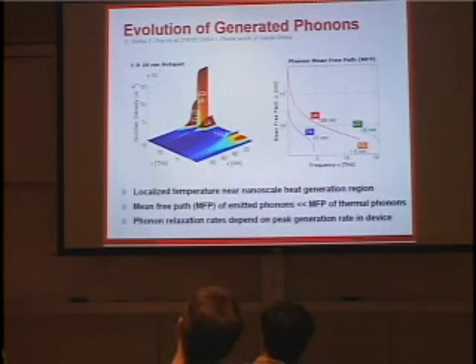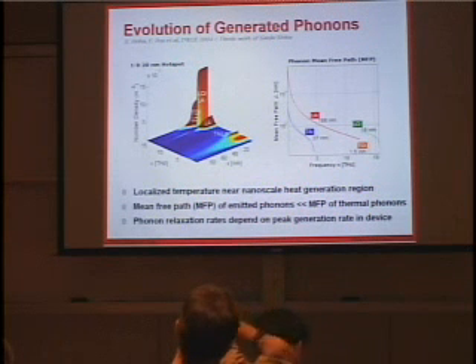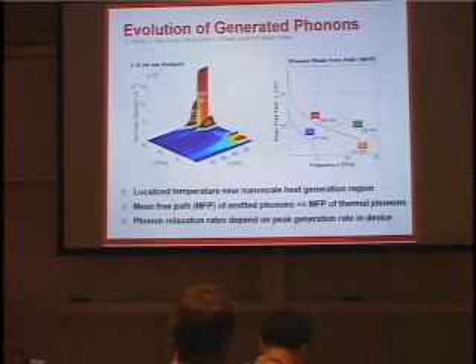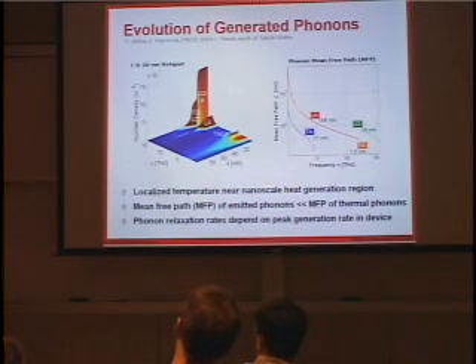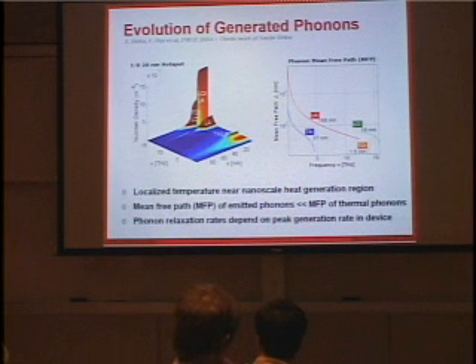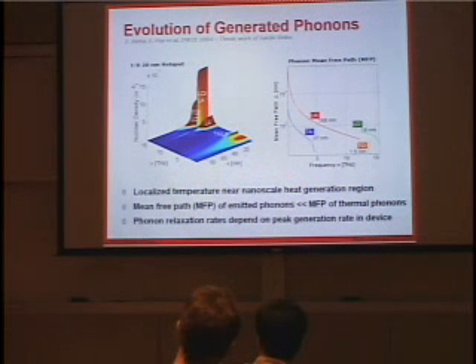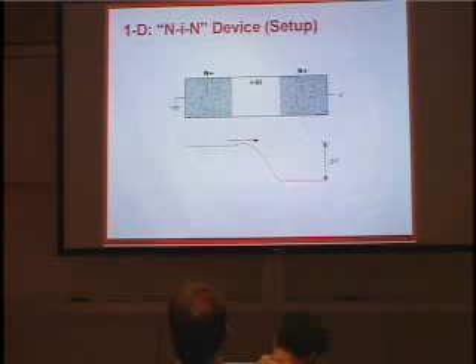So now we're trying to figure out how these phonons actually evolve in silicon. And one of the things that we're learning is that the mean free paths of these emitted phonons are actually a lot less than the mean free path of thermal phonons in silicon. So they're actually much more localized near the region where they're produced. They don't travel nearly as far. And also the other thing that we're learning is that the phonon relaxation rates actually depend on the peak generation rates in the device. And these peak generation rates are what I'm going to be talking about next in the context of the device and how they might be computed using this method and other methods.